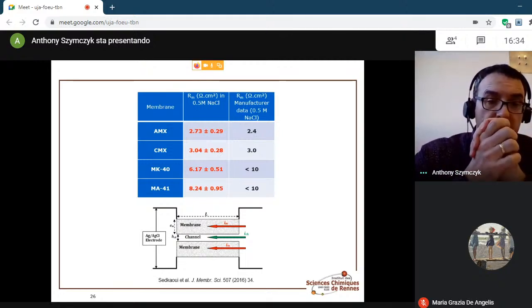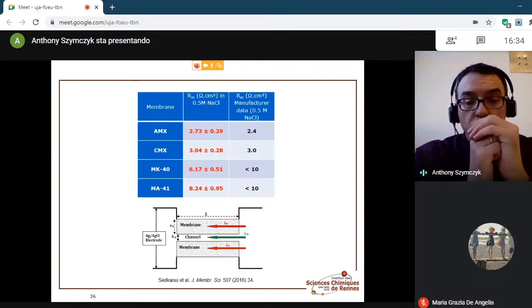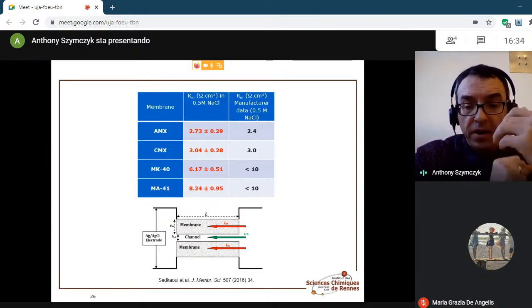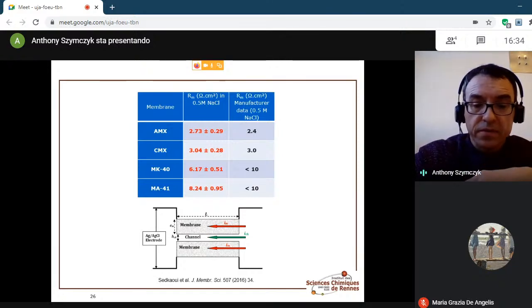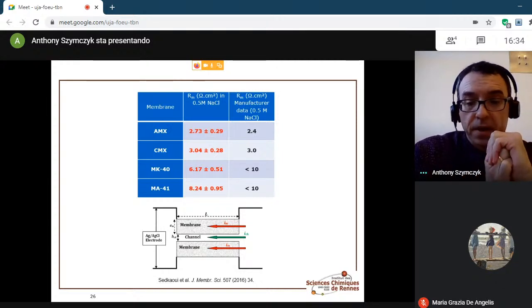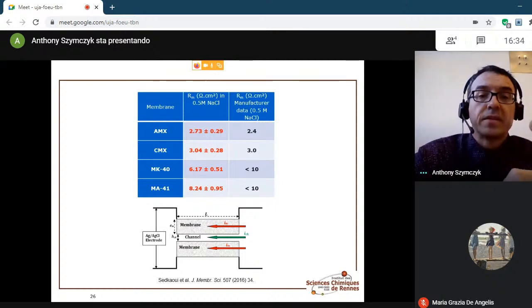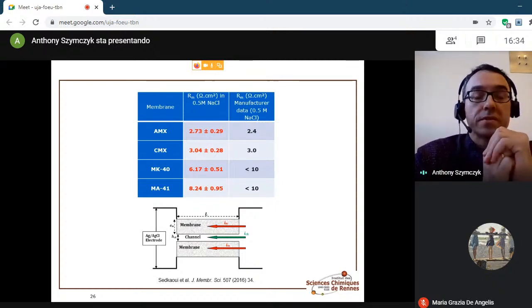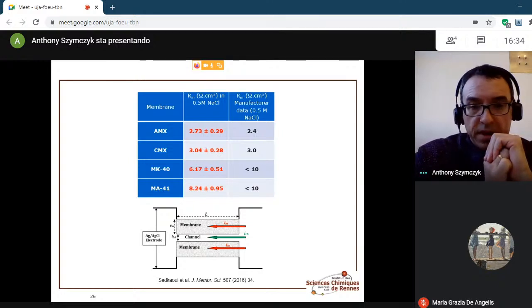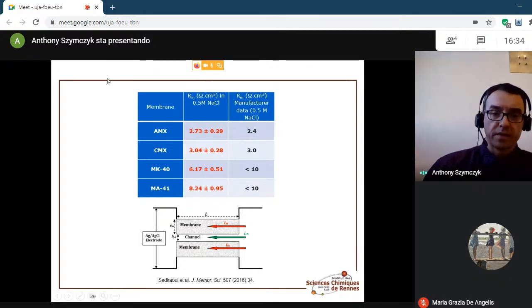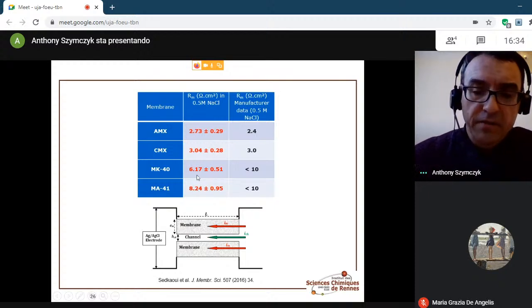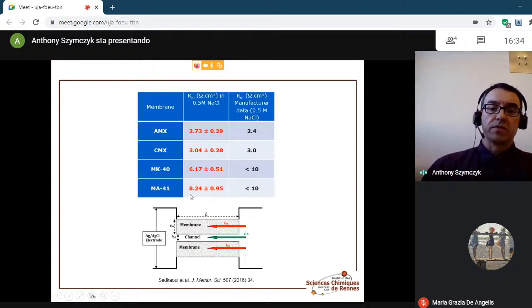As a last example, I show you here in this slide the values of the specific electrical resistances of different commercial ion exchange membranes determined by this type of tangential measurements of electrical conductance. So here we have both anion exchange membranes and cation exchange membranes. And as you can see in this table, if you look at the results printed in red, the values obtained by the tangential measurements of electrical conductance are actually in very good agreement with manufacturer data.